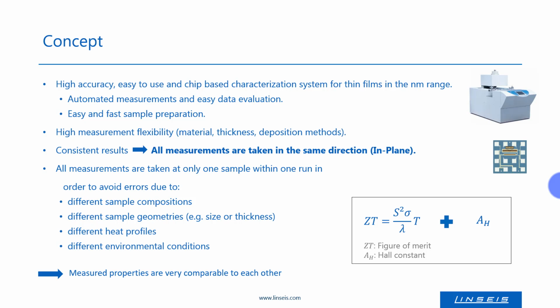As we can use the TFA as a platform, we can measure different parameters nearly simultaneously, and in the same direction, the in-plane direction. The TFA measures the thermal conductivity, not diffusivity, directly and can also be used to measure the specific heat capacity of thin films in a basic version. This version can be further upgraded for electrical conductivity and Hall constant measurements. From this, it is possible to get information about the charge carrier concentration and Hall mobility.